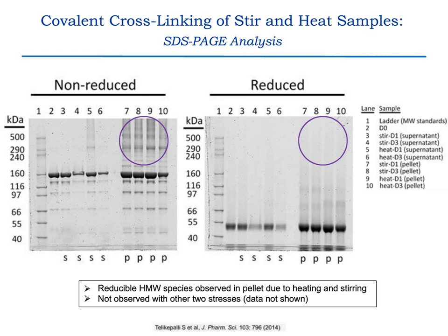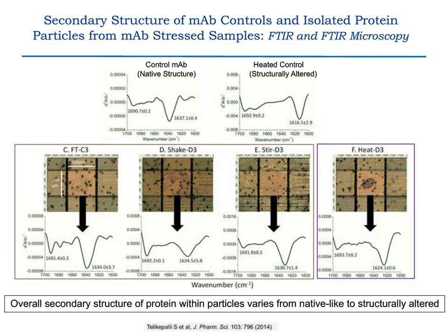In the next slide, we use FTIR to examine the overall secondary structure of the protein within the particle, and we compare that to two controls. The two controls are on the top, which is the control antibody, which is native structure, and an extensively heated antibody, which is a denatured control. And I don't have time to go through the details of FTIR, but you can see there's a main peak at 1637 inverse centimeters wavelength with the native, and in the denatured sample, that peak disappears and a new peak appears at about 1620 or so. And that corresponds to a change from the native intramolecular beta sheets to the intermolecular beta sheets